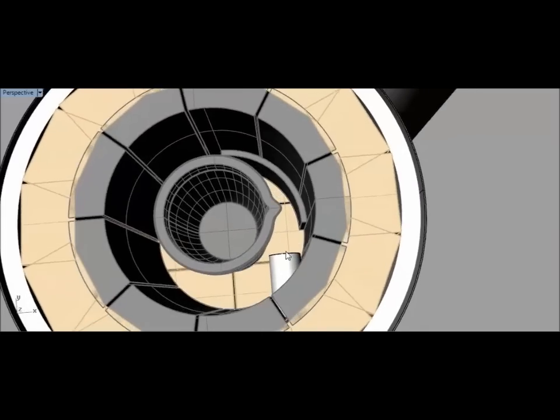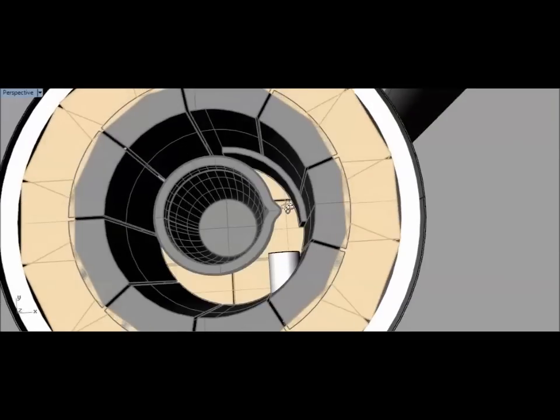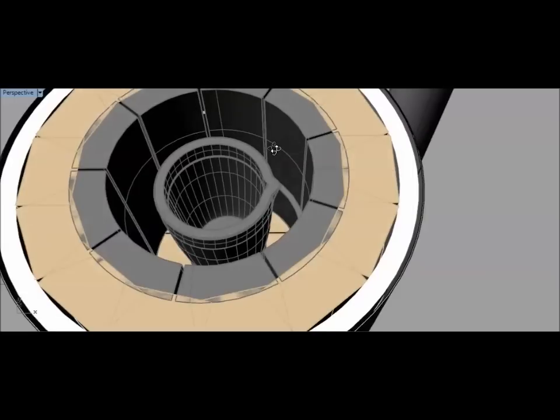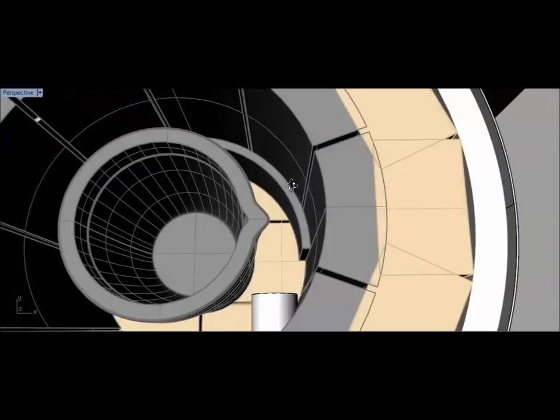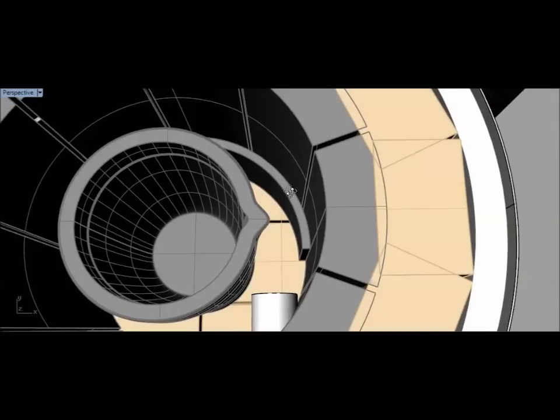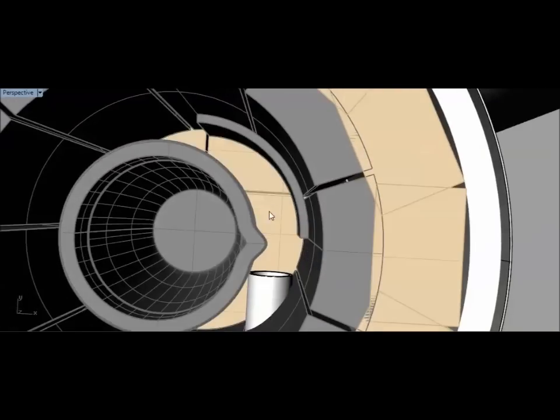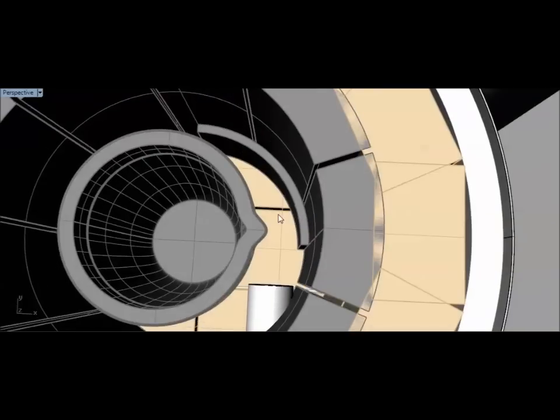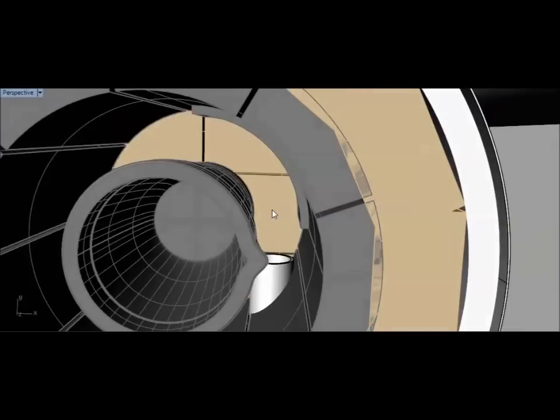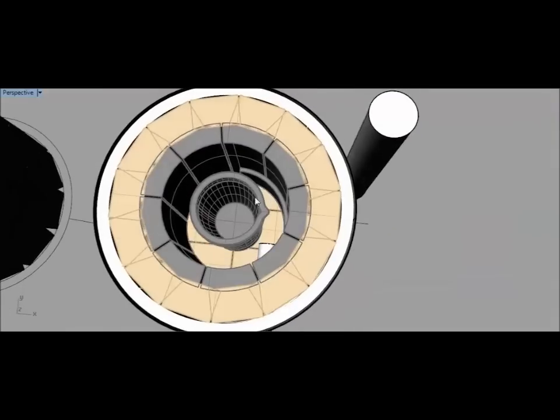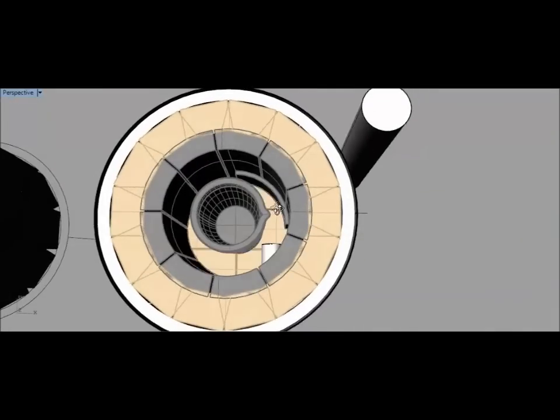And then I realized, as I'm looking at it, okay, you know, fire's coming out of here, oil's being sprayed, and then I realized, wait, oil's being sprayed? Hang on a sec. We're gonna have oil, sprayed onto the actual refractory. That's gonna destroy it. That's gonna destroy it. So I talked to my refractory guys, and they said, oh yeah, yep, it'll completely eat through it, eventually. Like, and I meant eventually, like, not very long at all. So, they said, the average person puts a brick there. I mean, I'm not gonna put a brick. I've got the ability to do CNC'd stuff. I'm gonna make myself a form that I can just lay in and out. So I decided to go that way.